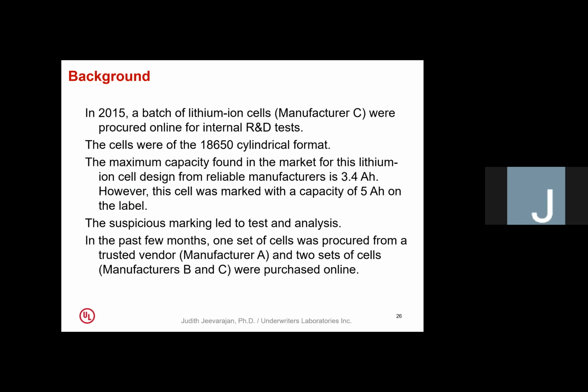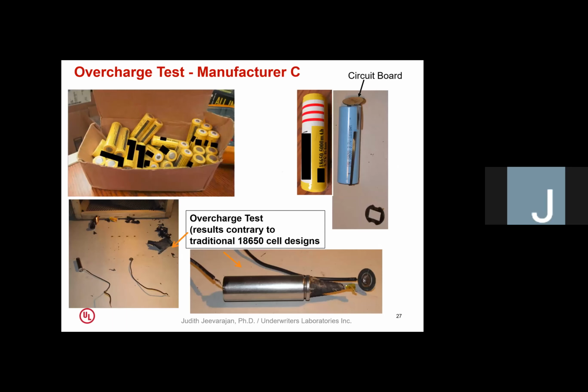And then, of course, in the past 2 years, we've done a lot more on this. So just showing you what we had purchased in 2015. This is what they look like, and these are the cans. The yellow label is on the outside can, and you can see it's labeled 5000 milliamp hours. When we measured the height, we actually found that it was taller than 65 millimeters.